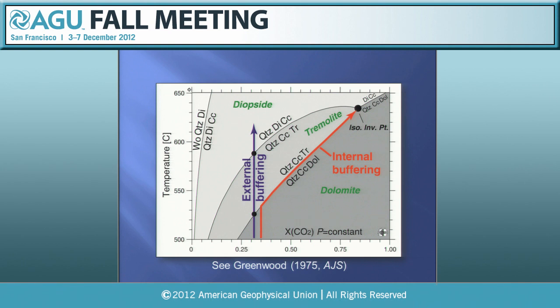Here, dolomite breaks down with other minerals to form tremolite, and the CO2 content of the pore fluid gets more and more CO2 rich until you reach an isobaric invariant point or maybe a consolute point. Okay? One thing to bear in mind on a diagram like this is that even at a constant temperature, say at 550 degrees in the dolomite stable field here, if you have infiltration of a water-rich fluid, you will move in this direction on the diagram into the stability field of a more reacted and decarbonated mineral assemblage.